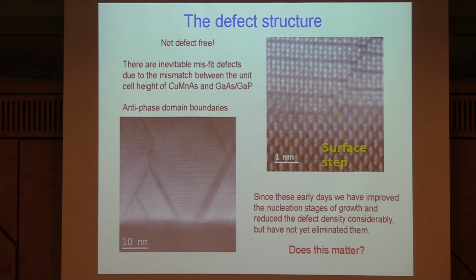And certainly very much in the early structures, I don't know if you can see this, it's quite clear, there's the gallium arsenide there, and you've got the copper manganese arsenide here, and you've got a step height, and it just doesn't fit. So it just breaks. These are actually called antiphase boundaries. Antiphase, as pointed out by the previous speaker, is a little bit of a misnomer, although that's the actual word used for these things. It's not really a different phase either side. It's the same phase either side, it's just displaced by half of the unit cell.